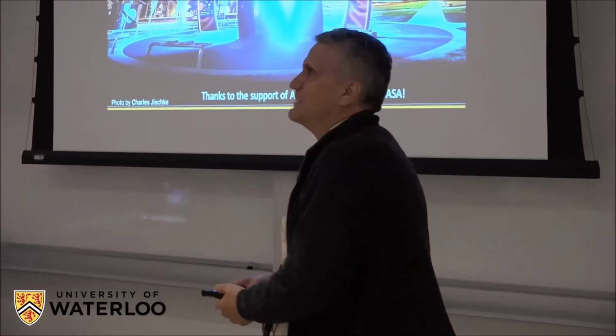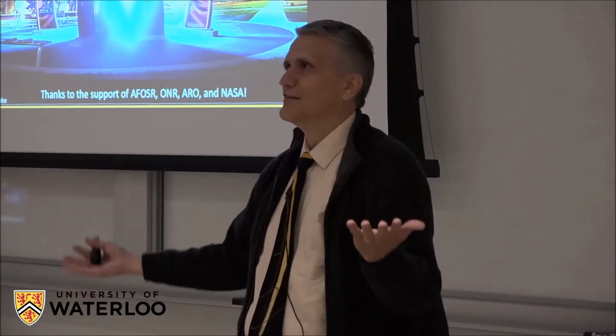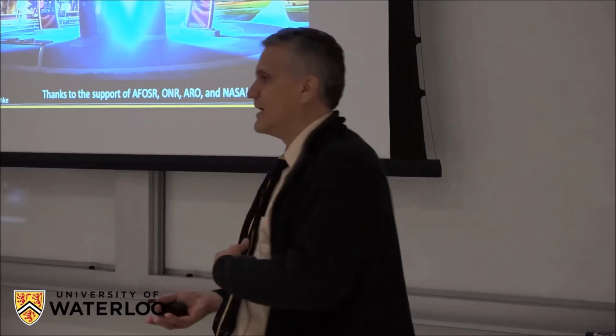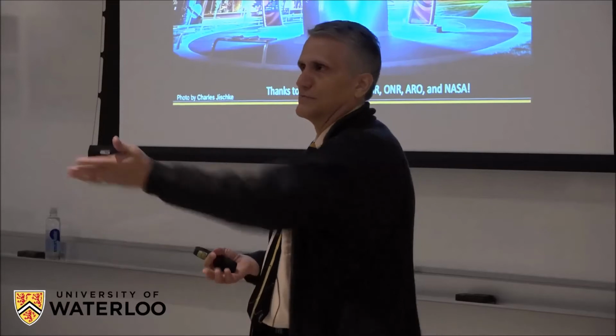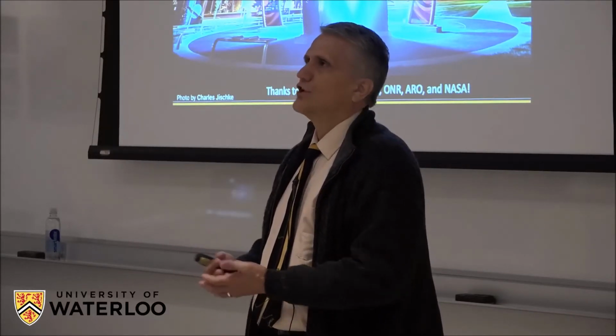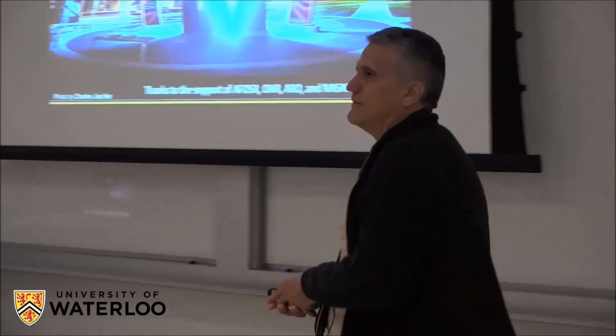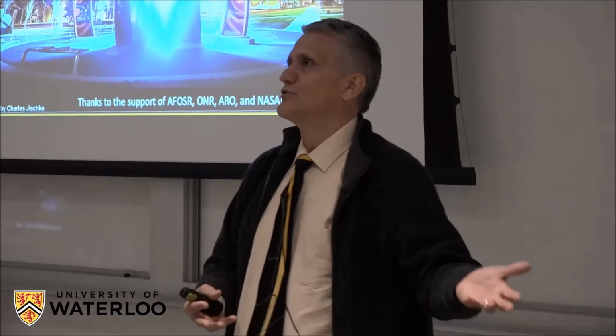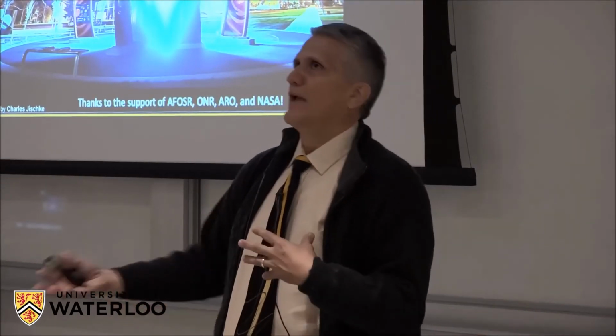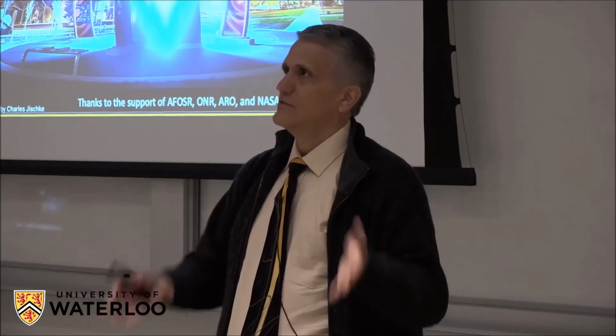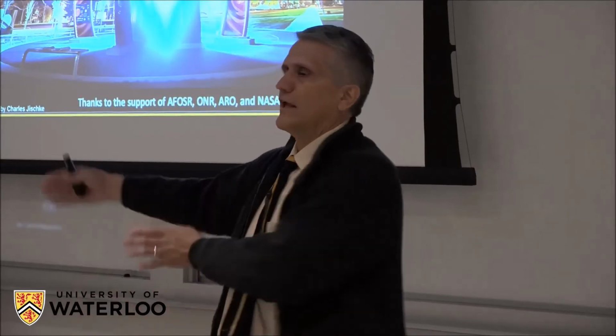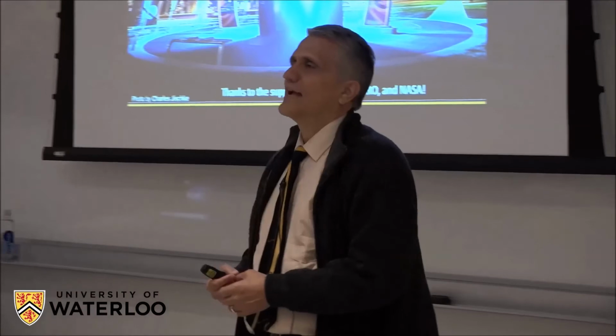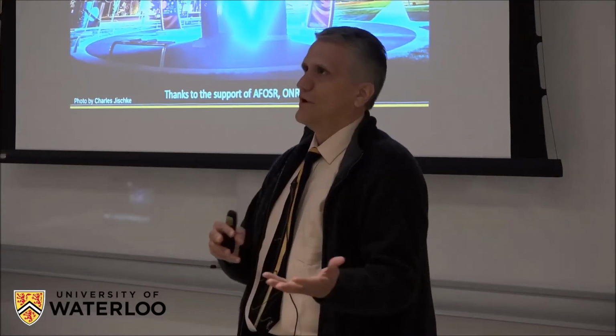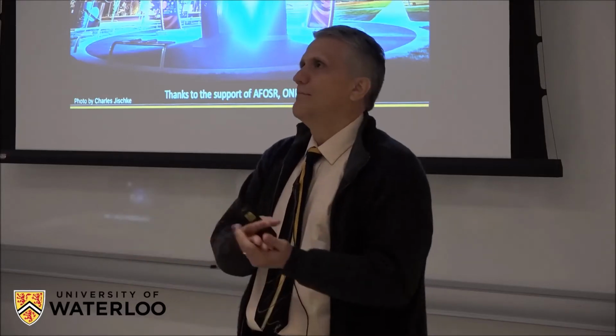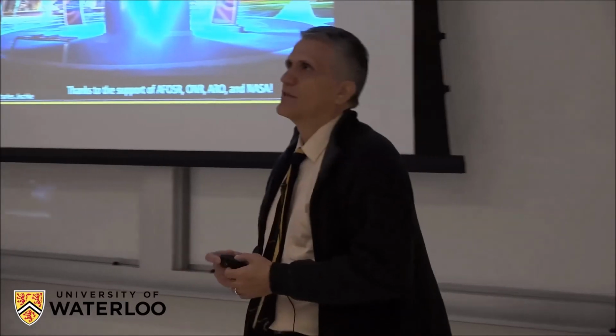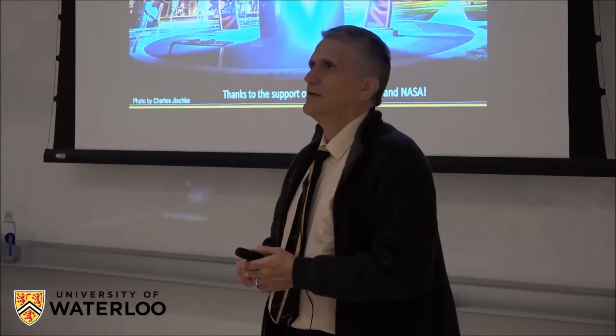That's an excellent question too, and you're always juggling that, and again with safety too. Nanoscale thermites, for example, can be really electrostatic discharge sensitive, and sensitive to friction and impact. Micron-sized powders of thermites are really difficult to ignite, very insensitive. So you may pick a size where you have the right balance: adequately insensitive, and a higher regression rate, burning rate, or reactivity that you're after. There are other ways to control that as well. If you have really fine particulate, you may bring in a binder or other material that will desensitize it adequately.